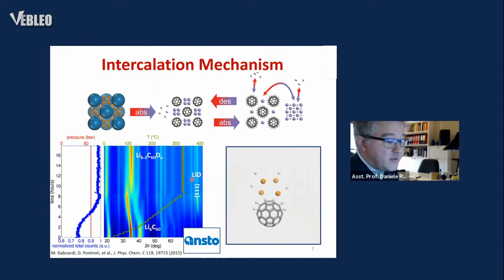It's worth noting that in this case the hydrogenation and the formation of the hydride happen at much milder conditions with respect to what is observed in the case of pure C60 and pure lithium hydride respectively. Moreover, in this case, the process appeared fully reversible, and after a thermal cycle, it was possible to recover the initial compound.